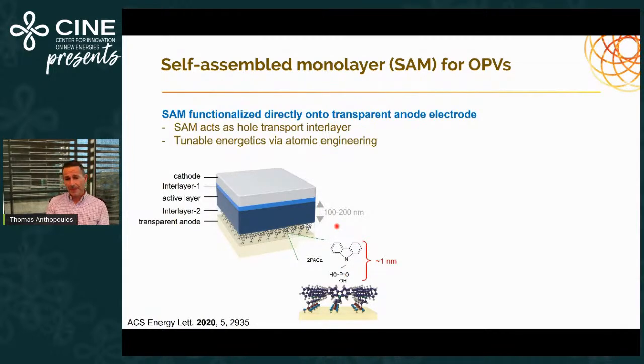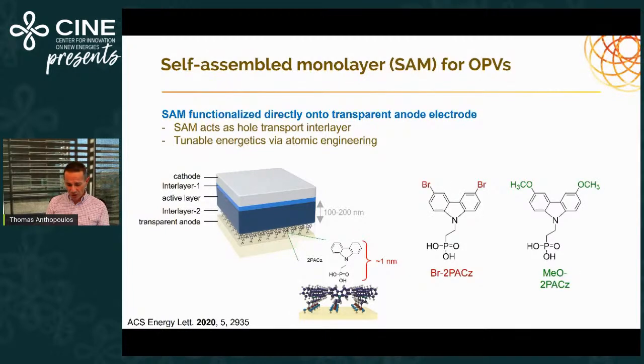So we quickly adopted the technology, got the material, applied it directly on the ITO, and created some OPVs. What we discovered is that these materials are very easy to functionalize on ITO. Surprise, surprise, this is well known, because the phosphonic acid unit acts as the head group, then we have the tail and the end group. The beauty of these materials is that the end group can be modified atom by atom through simple chemistry. The tail, of course, can follow a similar trend.